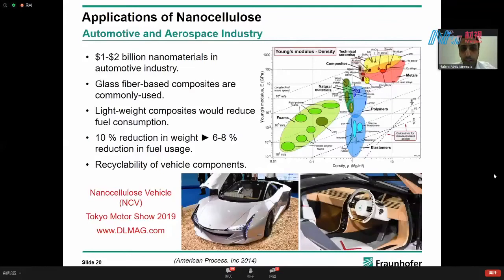Now we come to the automotive and aerospace industry, which are really interested in producing lightweight composites that are recyclable and also mechanically strong. This is of special interest to car companies in general, and it has to do with reducing fuel usage. In theory, if you are able to reduce the weight of a vehicle by around 10%, you are reducing fuel usage by 6 to 8%. Bio-based materials are attractive when they have pretty low density with very decent mechanical properties, which makes them really interesting for this kind of application. Here is an example of what's called the nanocellulose vehicle, which was shown at the Tokyo Motor Show in 2019. Many parts of this vehicle, obviously non-functional parts, are made of nanocellulose-based composites and also partly from wood.